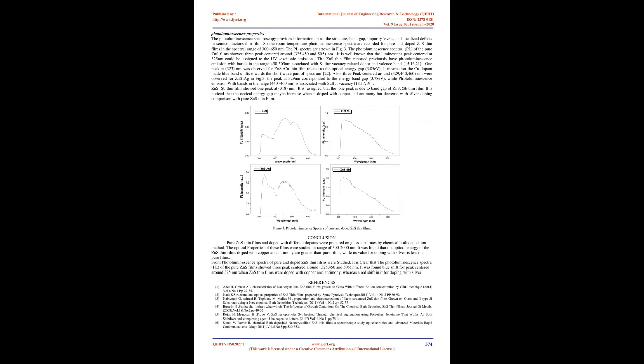On the other hand, the increase in the bandgap, or blue shift, can be explained by the Burstein-Moss effect 14. The Burstein-Moss effect results from the Pauli exclusion principle, and is seen in semiconductors as a shift with increasing doping of the bandgap, defined as the separation in energy between the top of the valence band and the unoccupied energy states in the conduction band. The shift arises because the Fermi energy lies in the conduction band for heavy n-type doping, or in the valence band for p-type doping, 14.